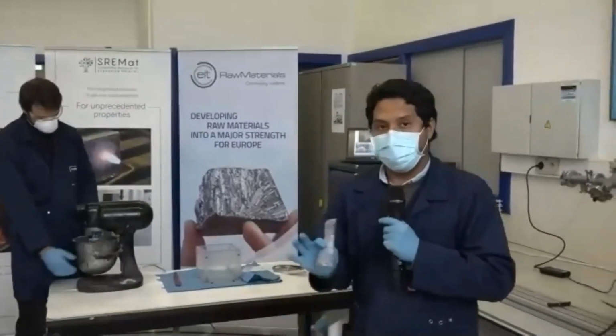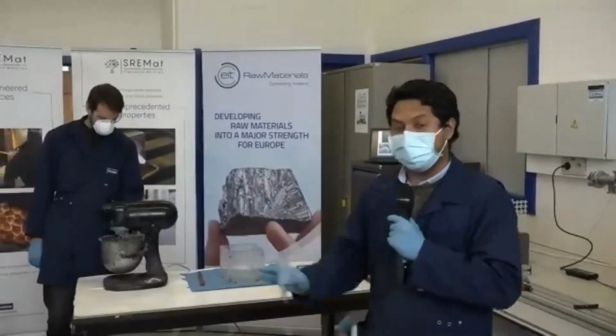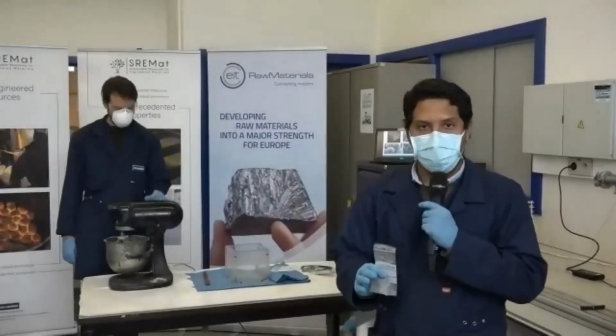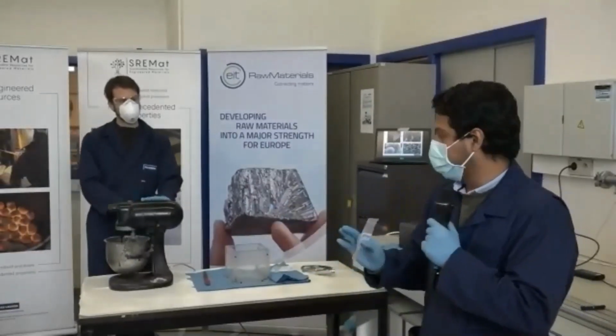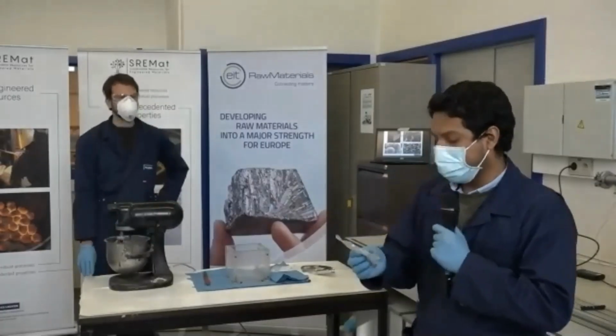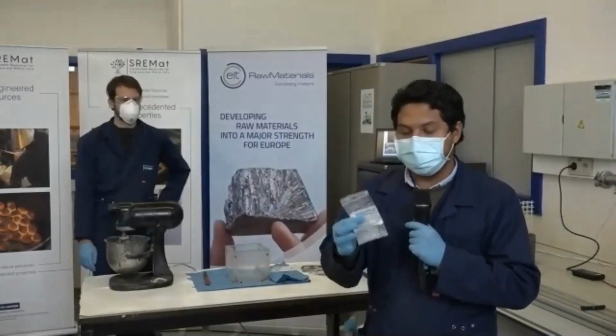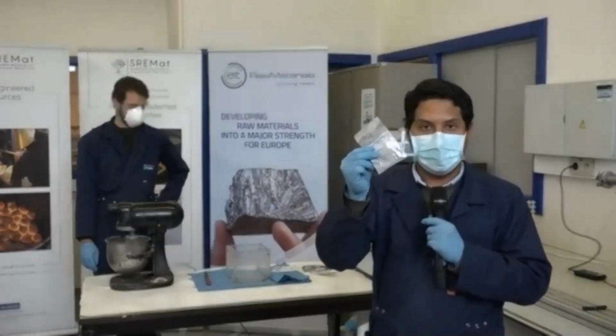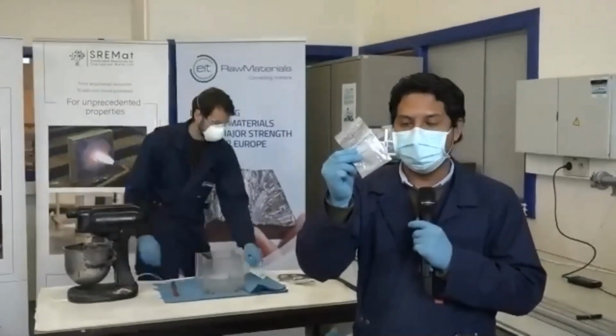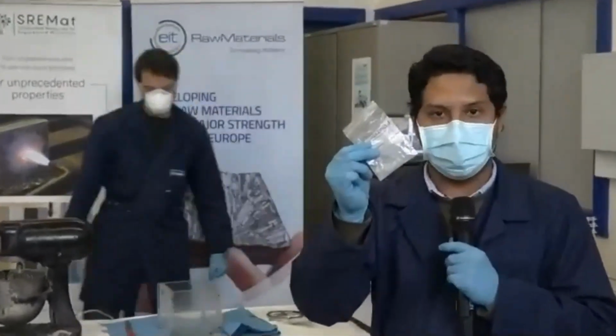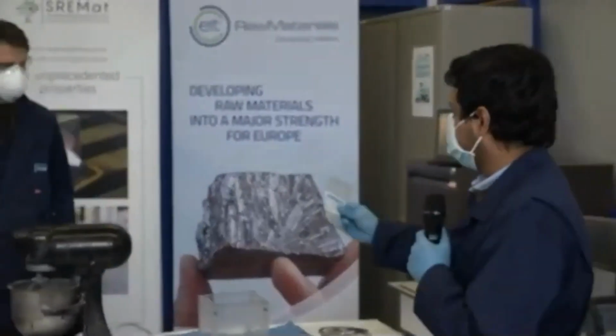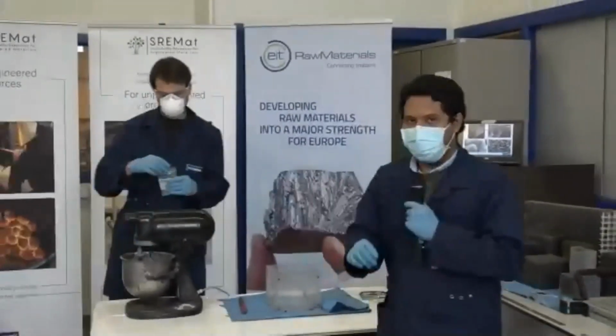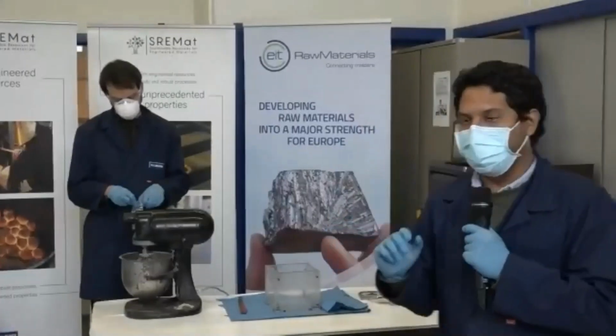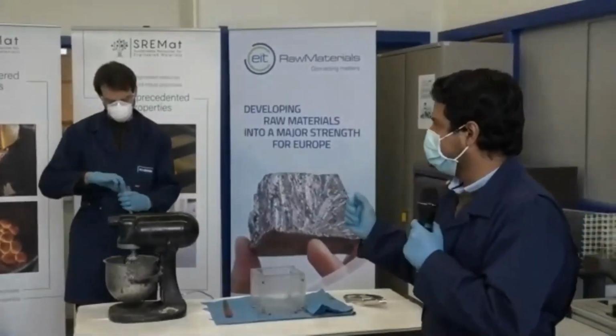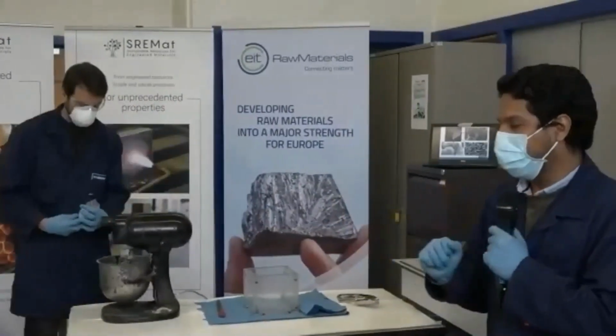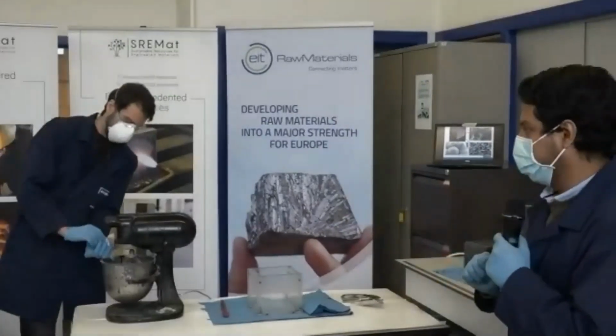Normally, when we are doing these things in the lab scale and also upscaled samples, we will mix for several minutes. But now we will do it a little bit faster. And the next and last component that we will introduce is this one. It is also a powder. We add it in very small quantities, and this is aluminum powder, metallic aluminum. I will hand it to Toby. He will add it to the paste. He will mix for around another 30 seconds. And then I will explain to you what is happening with that aluminum.